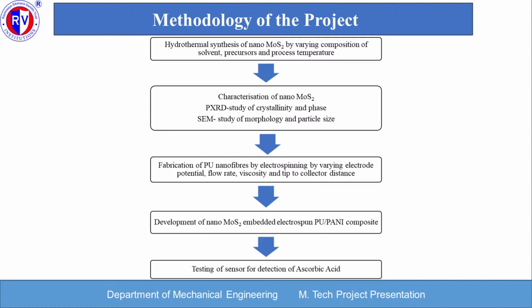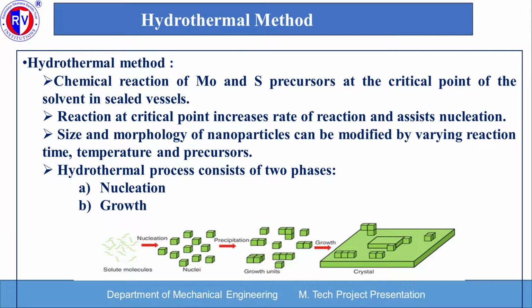This is the methodology we have followed in our project. First, hydrothermal synthesis of nano-MoS2 by varying composition of solvent, precursors and process temperature. Then characterization of nano-MoS2 by XRD and SEM, and fabrication of PU nanofibers by electrospinning by varying electrode potential, flow rate, viscosity and tip to collector distance. Development of nano-MoS2 embedded electrospun PU-PANI composite. Testing of the sensor for detection of ascorbic acid.